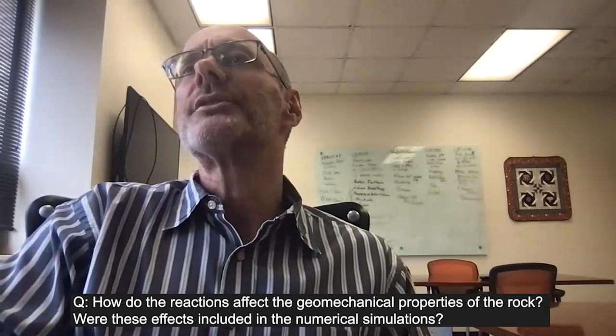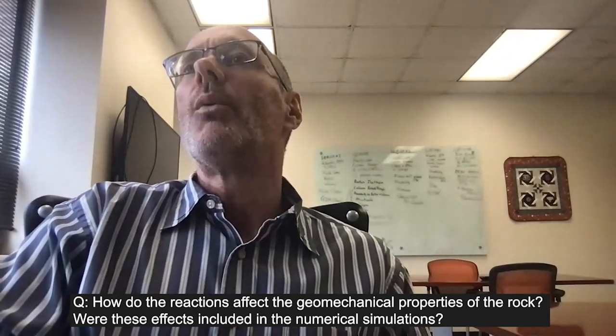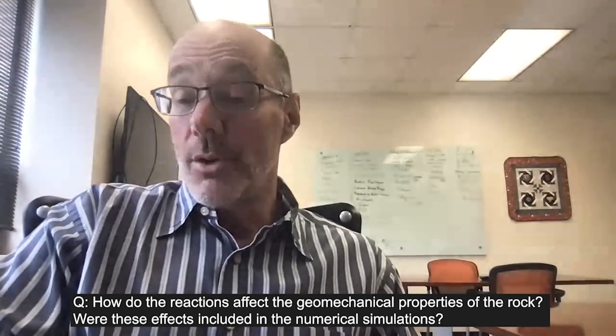How do the reactions affect the geomechanical properties of the rock? Were these effects included in the numerical simulations? So in terms of the things that we measured, and this would be collaborators, I'm not a geomechanics person, we measured fracture toughness, which is a measure of how easily you can displace grains as you're dragging that stylus across the surface of the rock. And so basically, as you dissolve away these cementing carbonates, those grains pop out more easily, and so you decrease your fracture toughness as that stylus is dragged across the top of that surface. The other way we did it was through strain release, where we put these asperities in contact with each other, move the samples relative to each other under compression, and then allow that strain to be released. And so that is also another measure of that geomechanical integrity.